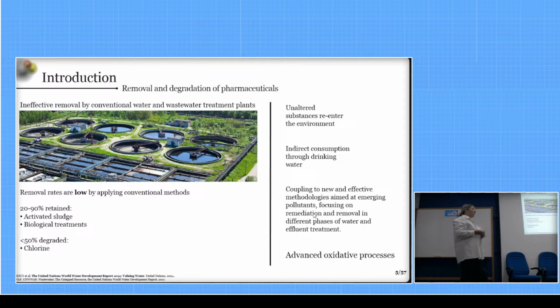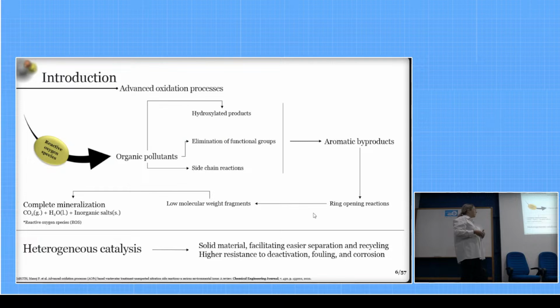One example of these new methodologies are the advanced oxidative processes, which are based on the production of reactive oxygen species, such as hydroxyl radical, and these species interact with the organic pollutants, resulting in hydroxylated byproducts, elimination of functional groups, and side chain reactions. This will lead then to the formation of aromatic byproducts, ring opening reactions, leading to low molecular weight fragments, which are desired for easing the complete mineralization of these pollutants.